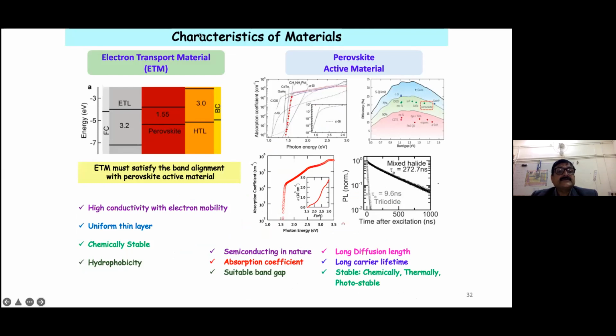I think this is simply the band alignment: the electron transport layer, the perovskite layer, and the hole transport layer. The band alignment is given. Perovskite active materials. This is the graph showing up to what frequency region you need more and more absorption coefficient. You can see that the absorption coefficient is higher above 1.5 electron volt.